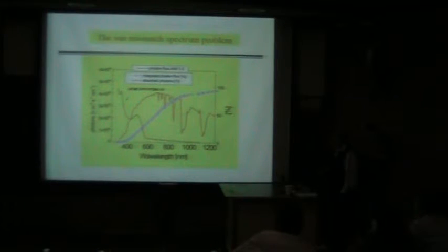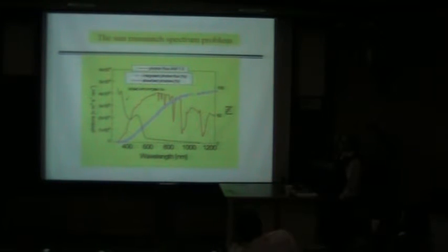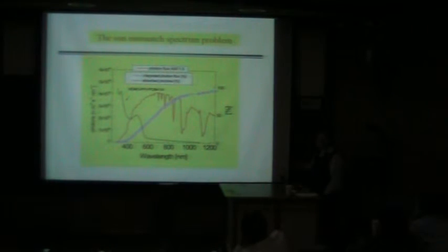However, our biggest problem in organic photovoltaics right now is a mismatch with the sun's spectrum. This is the sun flux on Earth. Disregard some absorption due to water. Our absorption for organic photovoltaics starts at 600 in the visible band, and we want to extend it to 1,000. And so we have to synthesize new polymers, and I want to add that we have chemists who synthesize for us all kinds of materials. This is very important to be self-contained in this business.